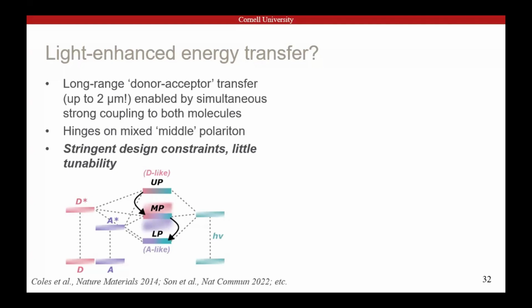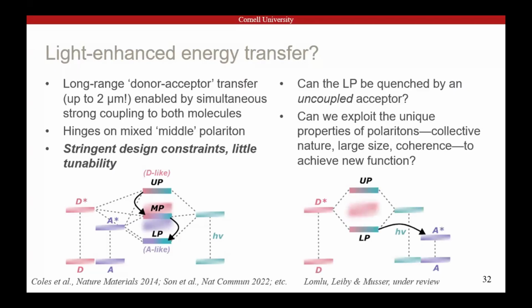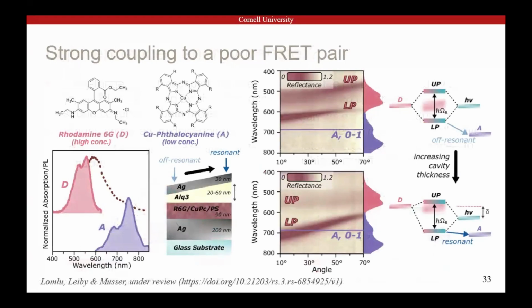So we wanted to step back and think, could we get this same behavior when the acceptor is not in the strong coupling regime? Basically, can the polariton just be quenched by an acceptor that is not itself strongly coupled to the cavity field? Because if it can, we can start to use all sorts of tricks of chemical analysis to understand properties of the polariton. And this took a remarkably long time to set up, because it's very hard to find the right pair of materials. We eventually settled on this very poor donor-acceptor pair, rhodamine 6G donor, copper phthalocyanine acceptor, which have pretty poor spectral overlap. These are spin-coated in a polystyrene matrix.